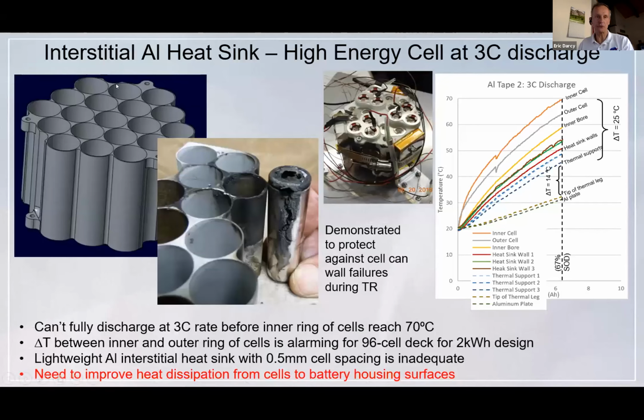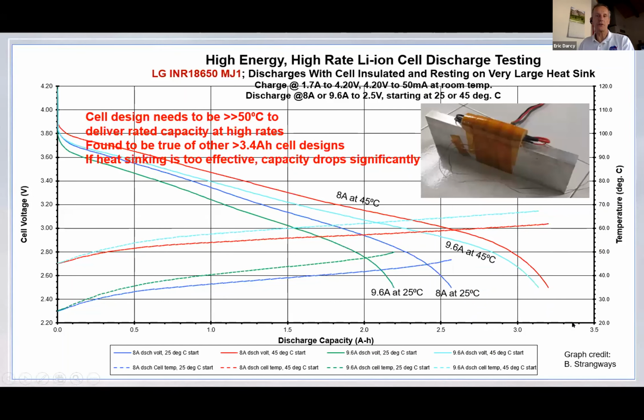We found that when you try to push this type of approach with a very thin interstitial aluminum heat sink, which amounts to about a 20% mass fraction, you can't move the heat out very fast, and you get large temperature gradients between the inner cells of this hexagonal pack and the outer cells of that pack. And so it just won't work for a 3C or high rate discharge. We've got to go to a different solution. So then we start looking: how do we get the heat out of these cells?